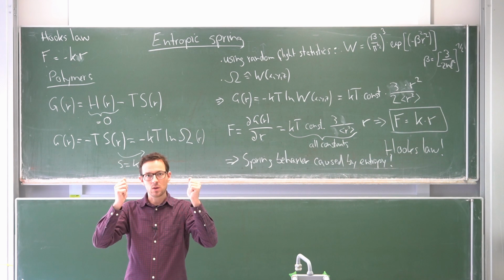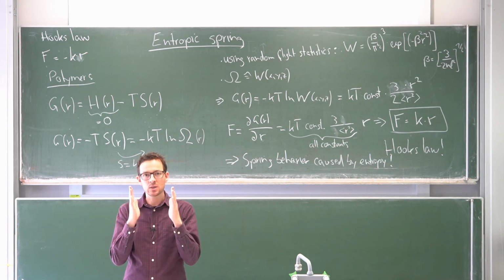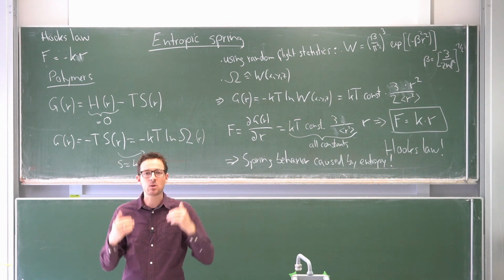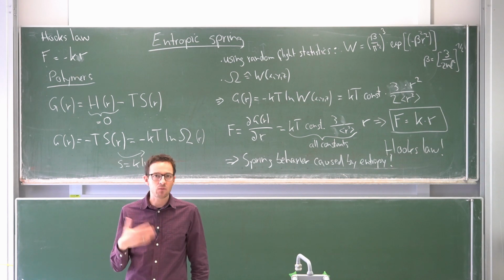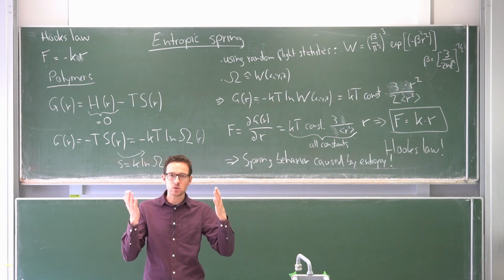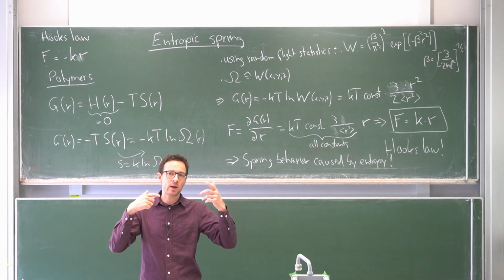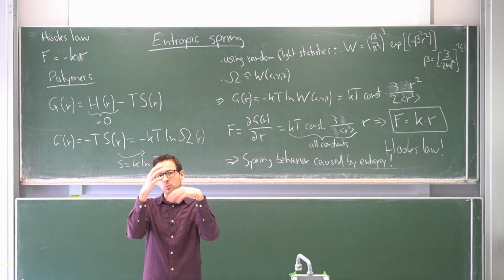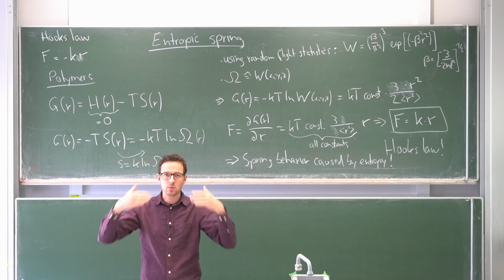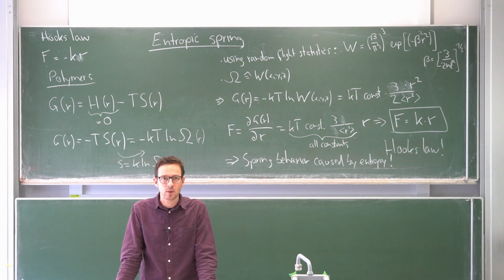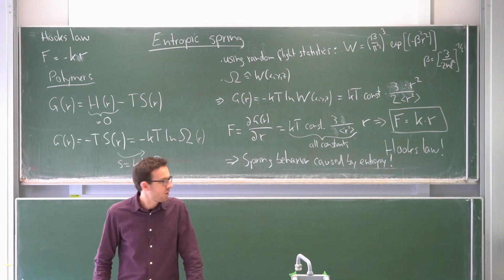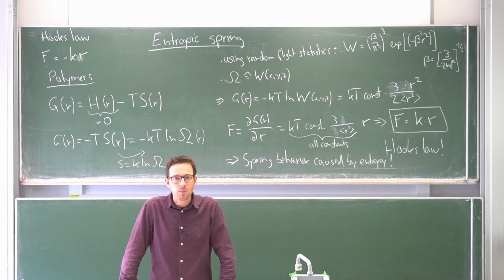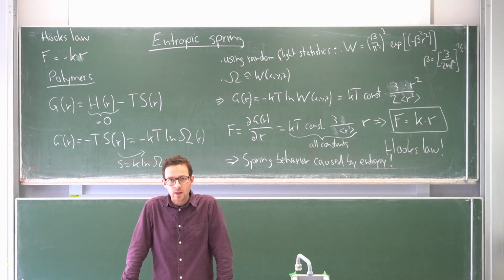If I let go, the entropy of the system increases, and this increase in entropy requires energy, which is taken from the heat of the surroundings. This is why it cools down. And why does it require energy? Because you can imagine the polymer coil doesn't entirely change by itself, but it changes by being hit by very small molecules all the time. And they nudge it more and more into a coiled state. This is what happens as we let go. This is where the energy is taken out of the environment. Okay, so these considerations clearly explain how the rubber heats up and cools down while stretching and expanding.